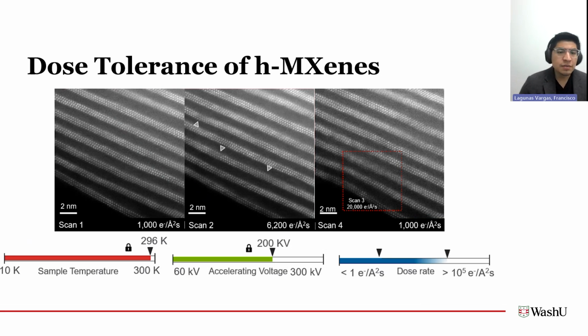So you can see from these images at about 1,000 electrons per angstrom squared, we have this nice layered material. So this is our hybrid MXene. And you have those bright regions, which are your titanium columns. And then between those bright regions, those bright bands, we have a dark region, which is where we expect the organic surface group to be.